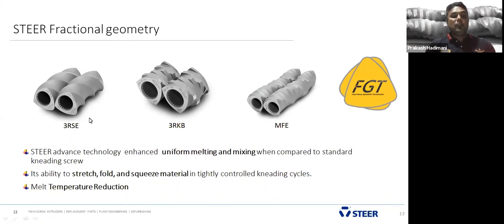3RSE, eccentric conveying elements, convey the material into the next level. Advanced technology. And 3RKB gives uniform melting through the system. There is no variation in shear rate, the uniform shear rate, and also gentle melting takes place in the polymer, and all MFE, melt formation elements, act as a stirring effect, stretching and folding and squeezing the material in the kneading cycle, and also reduce the melt temperature.